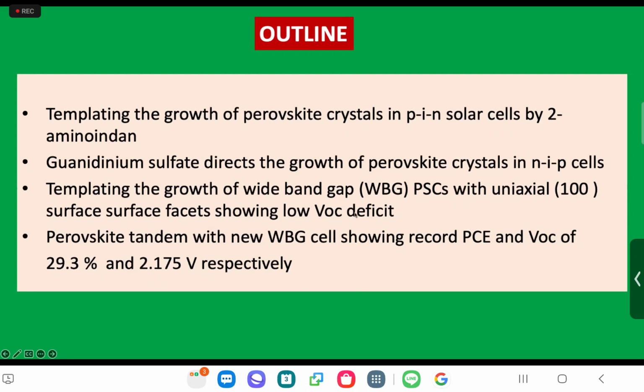And at the end, we show that actually by using this templating approach, we can make a large bandgap, 1.7 eV, that have about 1.37 volts open circuit voltage. And with that, we can reach those numbers here with the tandems. And I feel that the perovskite tandems, probably I'm getting a lot of enemies now, but they're more promising than silicon tandems.